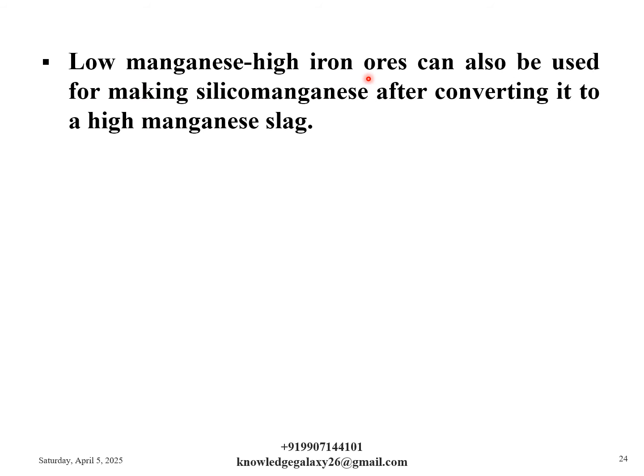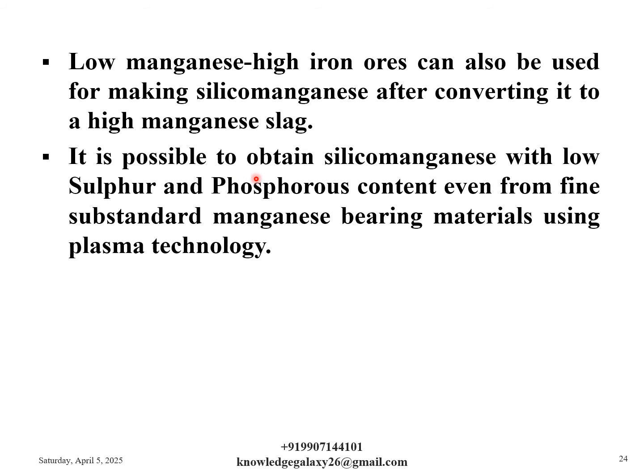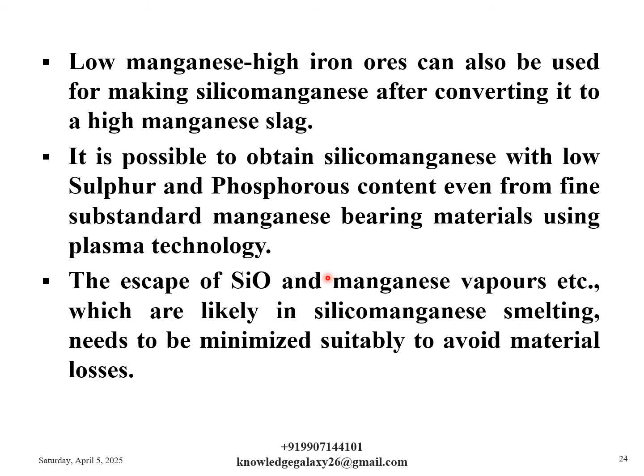Low manganese, high iron ores can also be used for making silicomanganese after converting them to a high manganese slag. It is possible to obtain silicomanganese with low sulfur and phosphorus content even from fine substandard manganese bearing materials using plasma technology. The escape of SiO and manganese vapors, etc., which are likely in silicomanganese smelting, needs to be minimized suitably to avoid material losses.